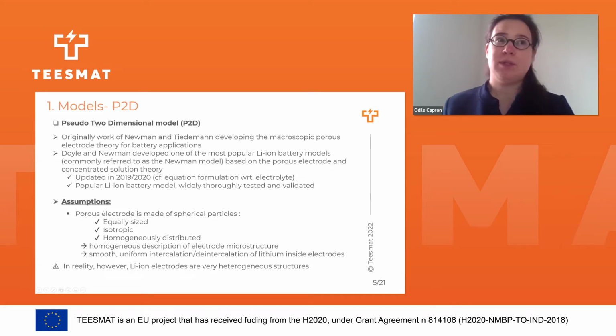But it's based on several assumptions that are important to mention. The two electrodes are represented in the battery cell, but they are considered to be made of spherical particles. These particles are equally sized, so they are assumed to all have the same size. They are also isotropic, and homogeneously distributed within the porous electrodes. Why do we mention porous? Because it also indicates that we are taking into account two phases. There will be mainly a solid phase, and the rest of the electrodes will be filled with electrolyte and also with binder. So these assumptions make this model consider a homogeneous description of the electrode microstructure.